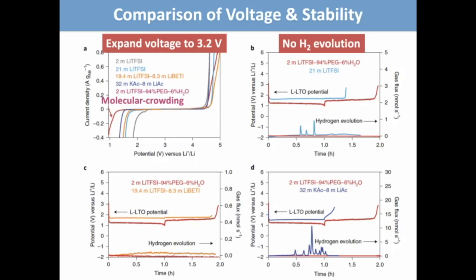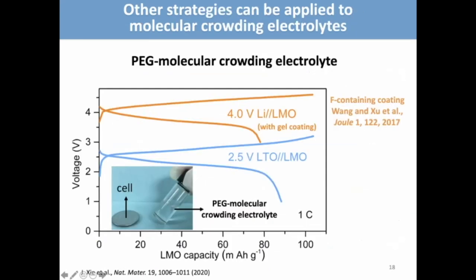Also, some electrolytes may give you a wide voltage window, but in real battery operation, you may still see hydrogen evolution. So we compare in parallel the PEG molecular crowding electrolyte, labeled in red, with highly concentrated electrolytes, and you can see that we can still see some hydrogen evolution in some of the highly concentrated electrolytes. So these are the small side reactions that we need to further reduce, but using molecular crowding, it seems to be quite stable in terms of suppressing HER.